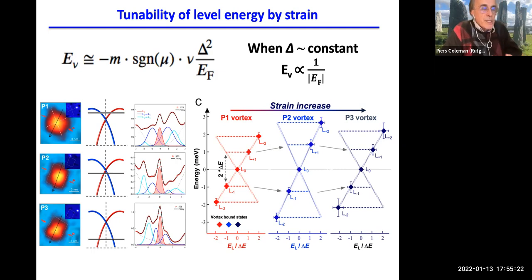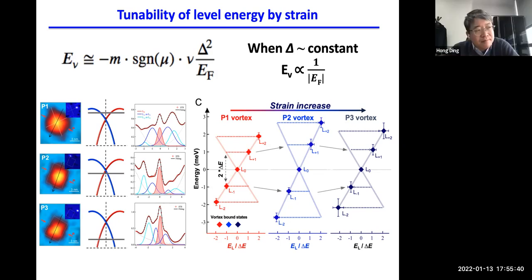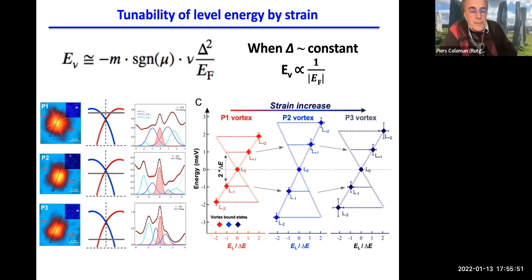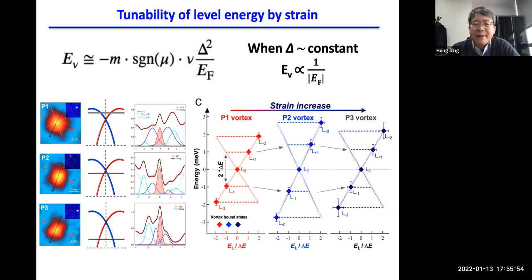Okay. Thank you. All right, Pierce. Yes, I had two questions. One was, what fraction of your vortices exhibit Majorana cores in them? How often do you see that in the various materials you've looked at in the vortex core? Yes, we measured essentially three cases, the iron, tellurium, selenium. In that case, we have about 20 to 30% overall. In some lucky surfaces, we see more than 50%.